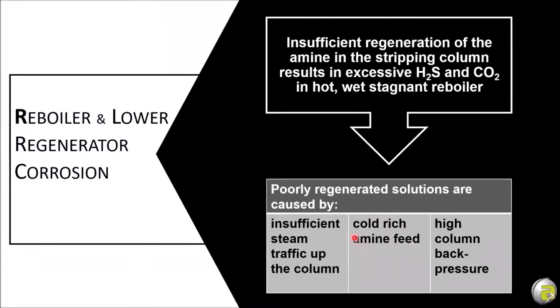You want to make sure that your lean-rich exchangers are working, that you don't have temperatures below 90, 95 degrees C rich amine feed temperature. And you have to make sure that you don't have a high column back pressure. The reason for that is the higher the reboiler pressure is, the higher the boiling point of the fluid, the harder it is to generate steam at high pressure. So our goal is to not have a high back pressure on the reboiler, so that we can generate the maximum amount of steam that we need to regenerate the solvent inside the column and not down in the reboiler.